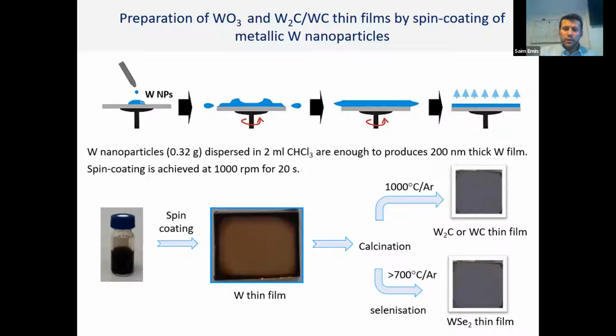After spin coating, we can decide for what purpose we can use them. We can use them for production of carbides or selenides. If we heat in an inert atmosphere at very high temperature, and if they are coated on a carbon substrate, we can produce metal carbides. If, for example, we put selenium precursor in the tube furnace, let's say selenium shots, which will evaporate at high temperature, then we can grow tungsten diselenide or molybdenum diselenide, depending on the type of precursor we use.